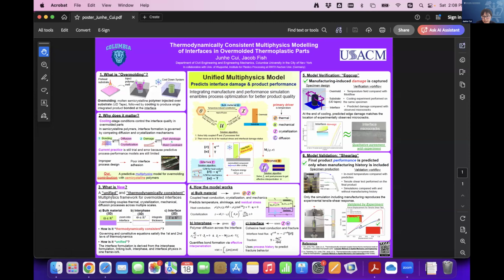And what's new in our research is that instead of treating the heat transfer, bonding formation, and part shrinkage as separate processes, we connect them with a unified and thermodynamically consistent framework across multiple domains: the bulk material, the nanoscale interface, and the zero thickness interface. It is thermodynamically consistent because all the equations satisfy the first and second laws of thermodynamics. It is unified because the zero thickness interface formulation is derived from the nanoscale interface formulation. So in this way, the physics stays connected across scales.